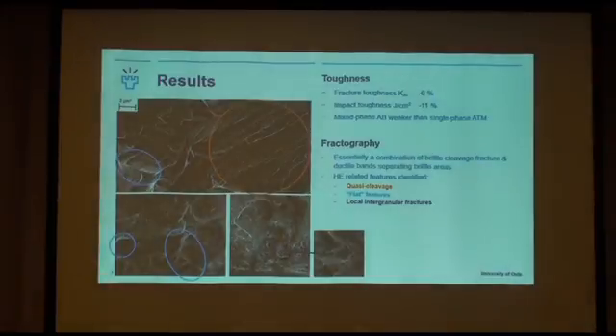So, results. In both fracture toughness and impact toughness tests, we get a decrease in toughness values at both temperatures, and both decreases are significant. And also the mixed phase microstructure was weaker than this single phase martensite, but further research will be done on those different microstructural properties later. And fractography shows essentially a combination of brittle fracture with ductile bands separating brittle areas, so very normal for this transition temperature region behavior.